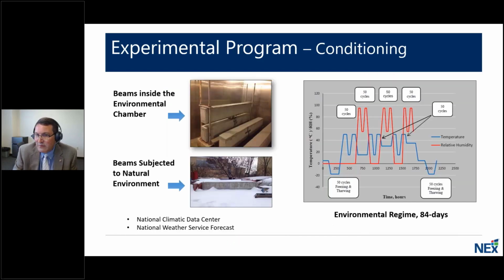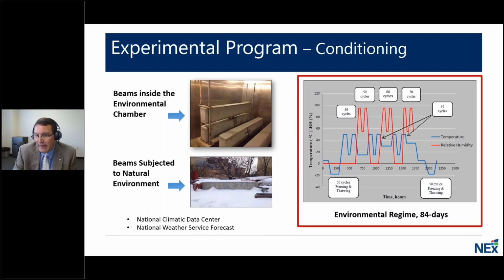As part of the environmental conditioning, an environmental chamber was used with the conditioning protocol shown here on the right. This accelerated regime simulates between 10 to 20 years of Midwest U.S. exposure to align with the desired service life for most repair systems. And so, for example, if we would be repairing a structure in the exterior environment, let's say it's a parking garage, let's say it's a bridge, when we talk to our Department of Transportation, they would be delighted if they could get 10 to 20 years of extended service life out of that structure.